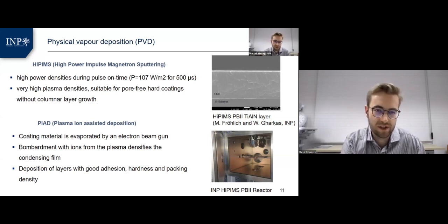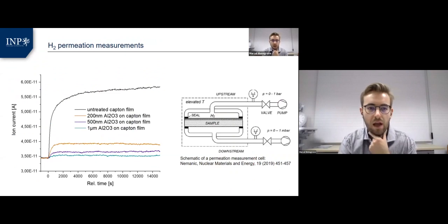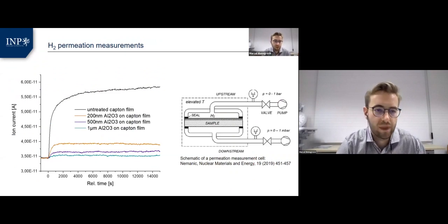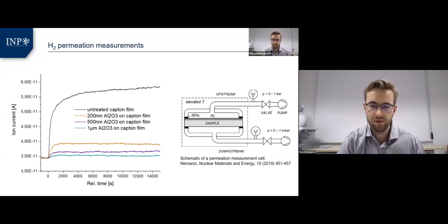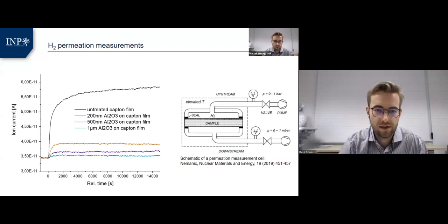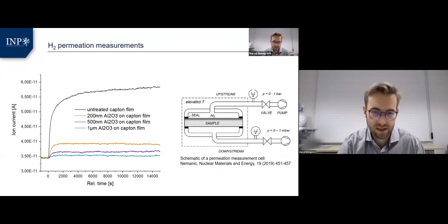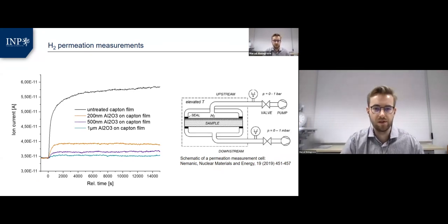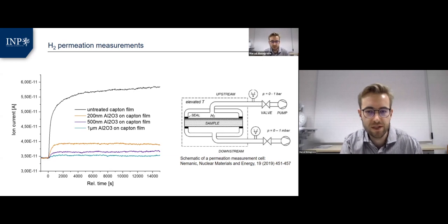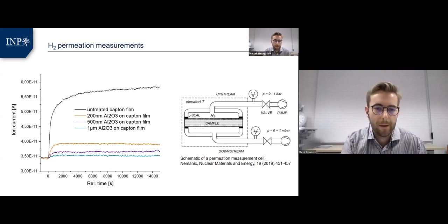enhance fast diffusion channels. Here you can see a fast permeation measurement that we conducted on a Kapton film using our in-house permeation measurement device. It was coated with different aluminum oxide films, and as you can see, using 1 micrometer of aluminum oxide, we are able to drastically reduce permeation.